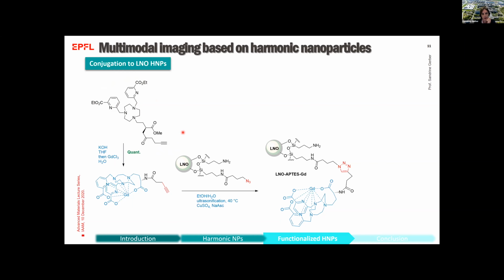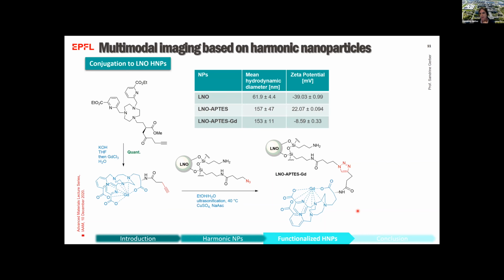From this intermediate ligand, upon saponification conditions, you can get to the chelation of the gadolinium ion. Then, by a click reaction at the surface of the lithium niobate coated nanoparticle, you end up with these conjugates, which combine the harmonic nanoparticle core with a gadolinium chelate.